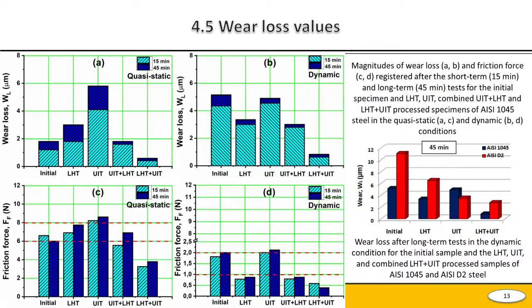And here we can see the results, especially wear loss and friction force, registered after the short term and long term tests for the initial specimens and those treated by the surface modification treatments. It's clear that the formed fine-grained microstructure coupled with high hardness and low roughness provides the smallest wear loss values. For instance, the rates of wear losses of carbon and tool steel after long-term tests in the dynamic condition were decreased by 84% and 75% respectively after the combined process. Next slide, please.